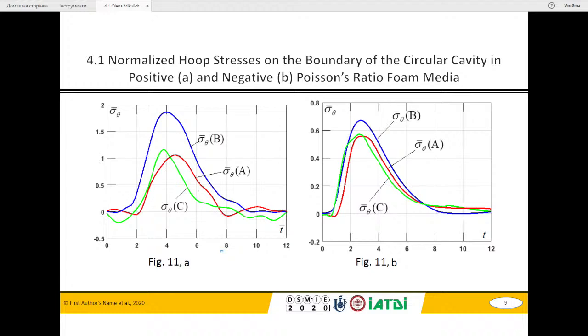The slide shows the distribution of normalized hoop stresses at several points on the boundary of the circular cavity. The left figure corresponds to the case of foam medium with positive Poisson ratio. The right figure corresponds to the case of foam medium with negative Poisson ratio. Foam with positive Poisson ratio was modeled using cellular elements. Foam media with negative Poisson ratio was modeled using re-entrant elements.